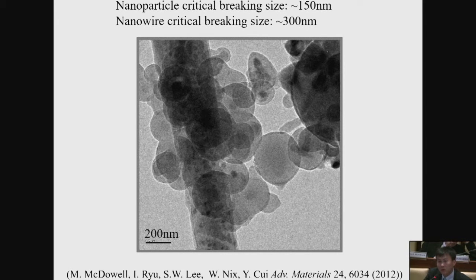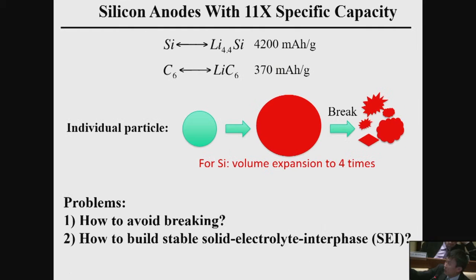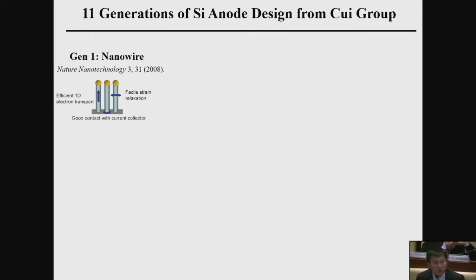Using a technique like this, we can identify how the materials is changed, what's the critical breaking size, to help us to design the right material to solve those problems. So these are the problems you see. For the very high capacity materials, it goes through this volume expansion from silicon particle become lithiated silicon, lithium silicide particles. And then it's going to be broken. Now the question is, how do you design the materials to overcome the breaking problem? And then how do you build stable interface between these particles and organic electrolyte? That's the research my group has been doing in the past 11 years at Stanford. So now let me show you the first generation of thinking, how do we overcome this problem?